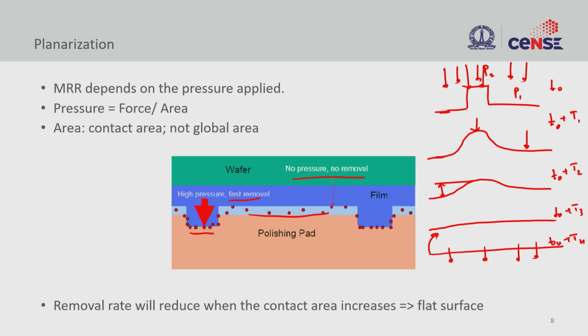So when the topography is reduced, you have a reduced force and reduced removal. So that is what this contact area is all about. If you increase the contact area, the pressure that you apply goes down and you will eventually reduce the removal rate. So you need to understand at what point of time that you should stop, right, in order to maintain the flatness and not lose material.